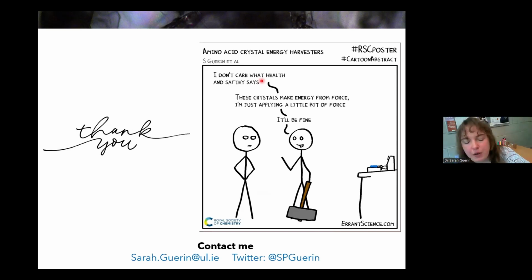Yeah, so we have two components to a piezoelectric response. We have our polarization tensor, which is our Coulomb per meter squared value. And then we have our elastic stiffness tensor, which is a 6 by 6 tensor from which we can derive our Young's modulus and all of those bulk properties.